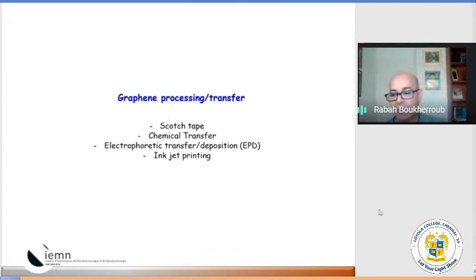Now, whether you buy the graphene or graphene oxide, or whether you make it, you have to transfer it. If you're with a CVD graphene, it's mostly grown on copper or nickel, but for a lot of applications, you want to have it on a different substrate. In particular, I will give you examples where we want to use it for optical sensing. So we have to transfer that for SPR, surface plasmon resonance. We have to transfer that onto a gold sample.